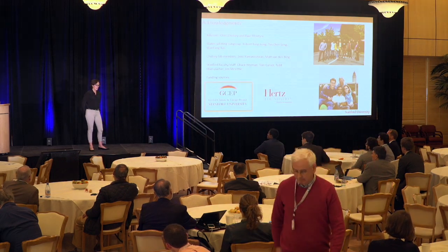So we've done grazing incidence X-ray diffraction to study what kind of crystalline phases we might have. It looks to be all amorphous. So even after annealing, we see very, very low intensity peaks for anatase TiO2. But in all cases, this material is predominantly amorphous. So we actually have more of a solid solution model for the iridium in the TiO2 as opposed to any kind of distinct crystalline phases.